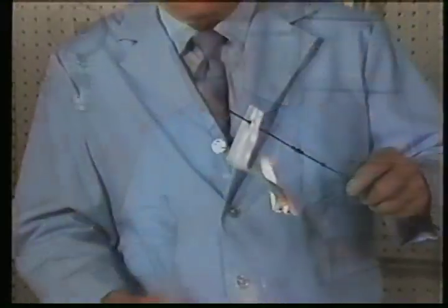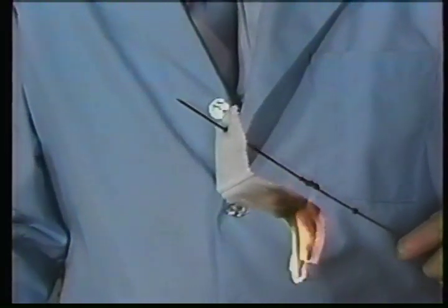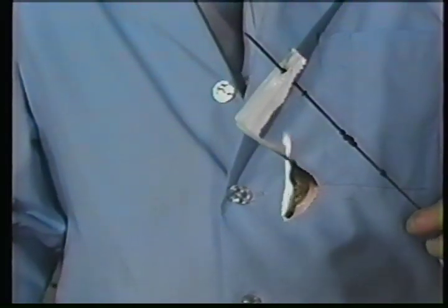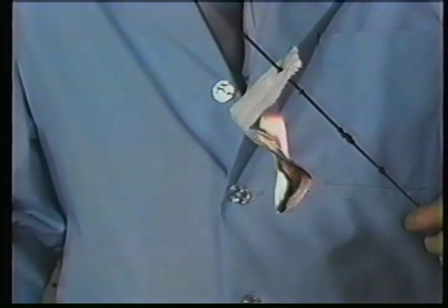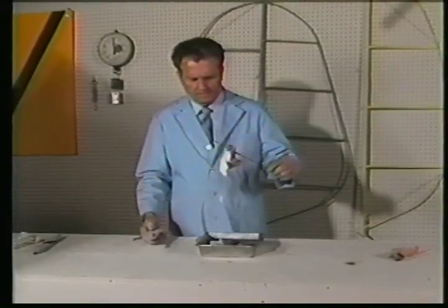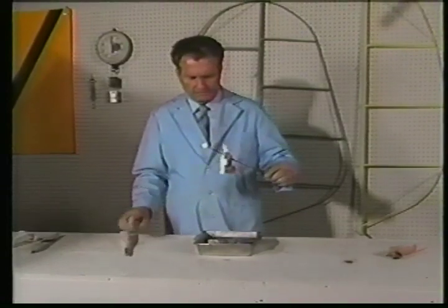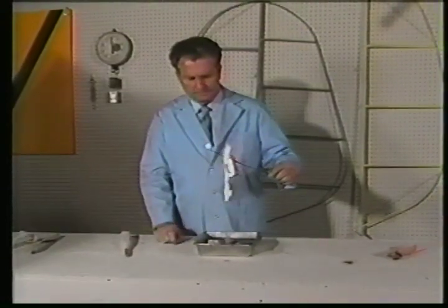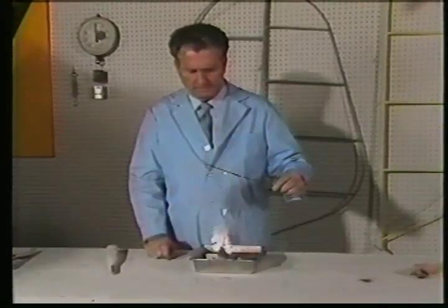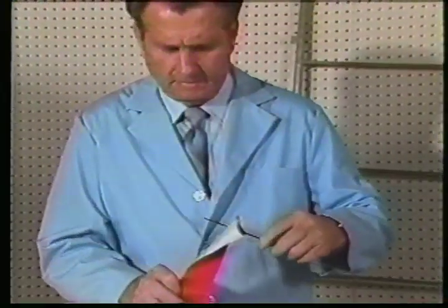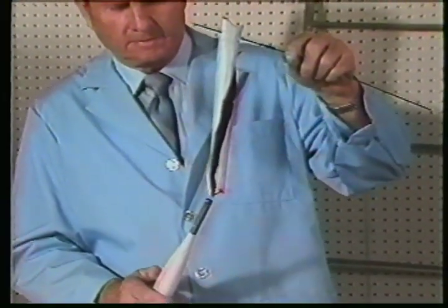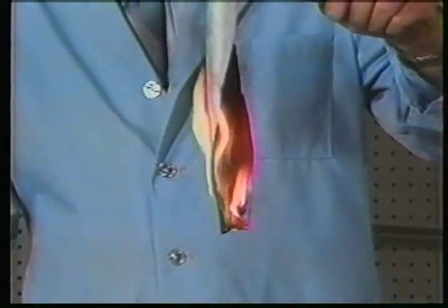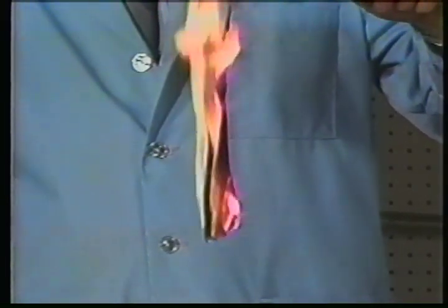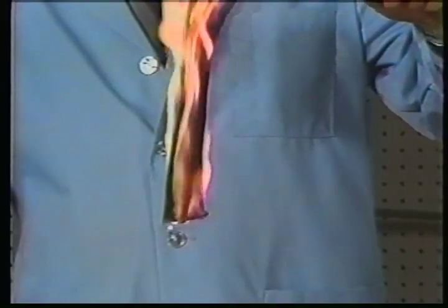The next specimen is clear butyrate dope on polyester. It has a burning rate a little less than the untinted nitrate dope. This sample is aluminum pigmented butyrate dope on polyester, which burns about the same as nitrate dope due to the aluminum pigments. Last, we have a sample of glass fiber completely finished with butyrate dope. The burn rate is about the same as butyrate on polyester, however, only the dope film burns, and the glass fiber is left intact with some of the aluminum pigments attached.